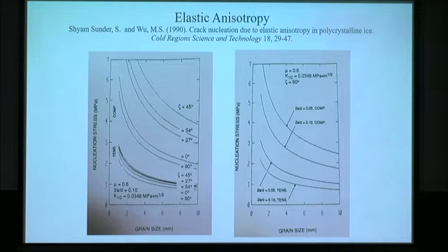This is just some more detail. This one plots the nucleation stress versus the grain size. It's the same kind of plot, but for various basal plane orientations. You can see 90 degrees is zeta, which is the c-axis orientation. At 90 degrees, we get a lower nucleation stress than if the basal plane orientation is 45 degrees. We have a rather widespread of results if the c-axis orientation changes. This broad spread of nucleation values is broader in compression than in tension. The results that we see below here refer to the tension results. So this is 90 degrees to 45 degrees.